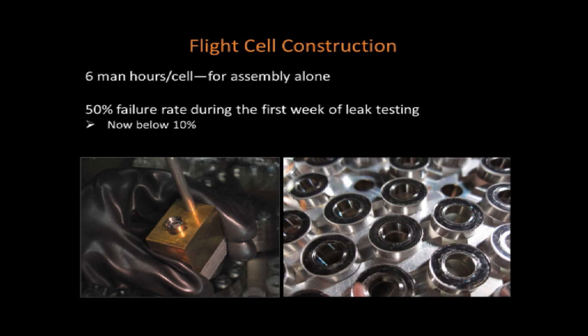We started leak testing, and I was actually terrified because we had a 50% failure rate on the testing for the leaks to see how airtight they are, to see how contained the cell actually is. And at the beginning of it, we were at like 50% failure rate, and now we're down to less than 10, so I'm thrilled about that.